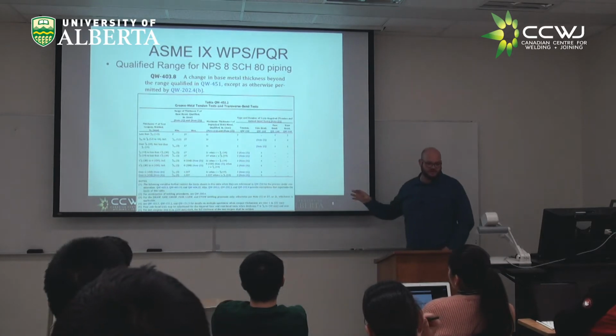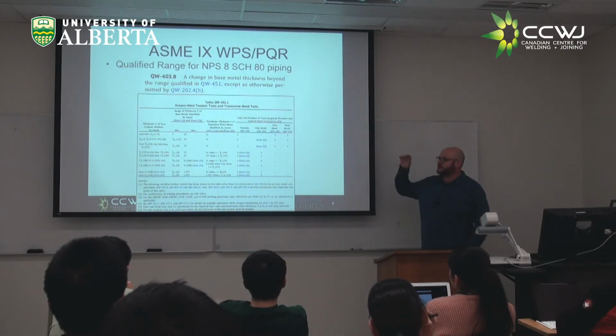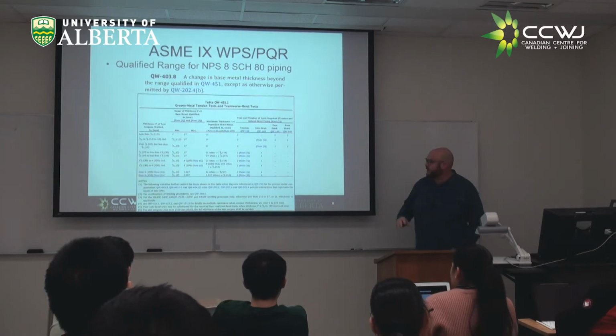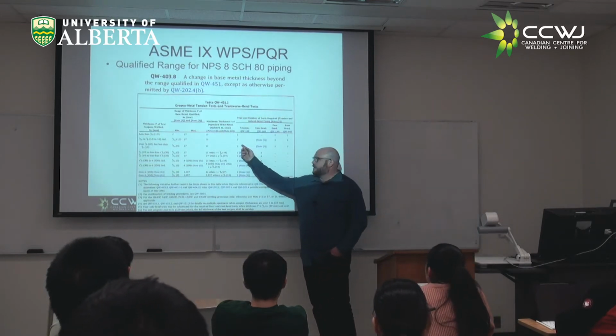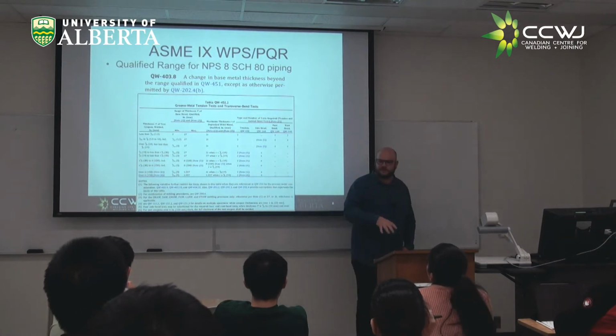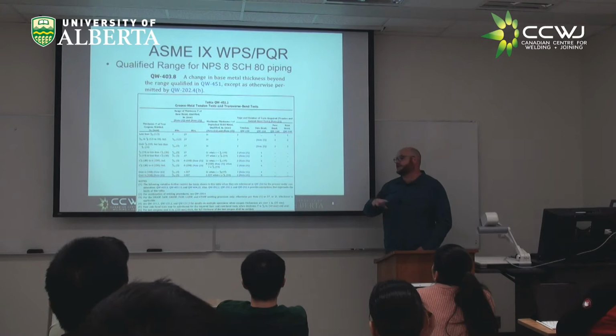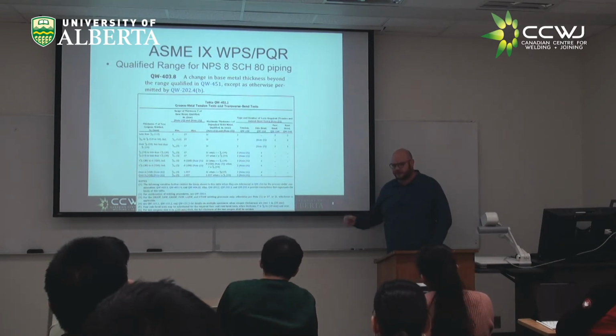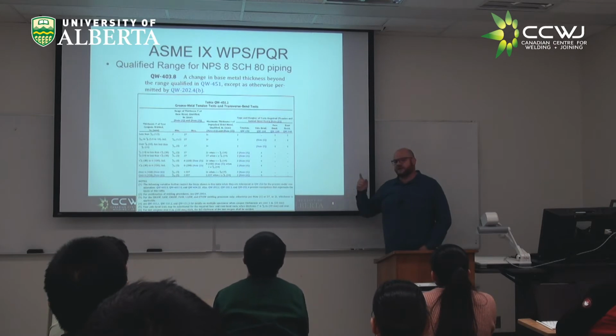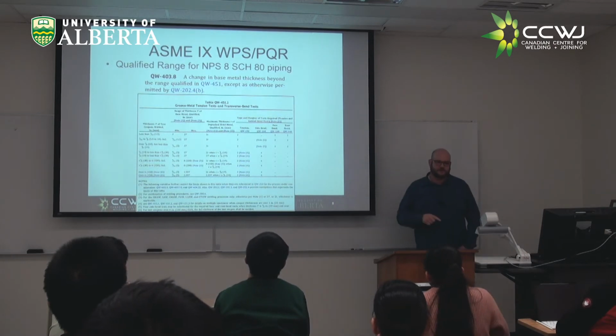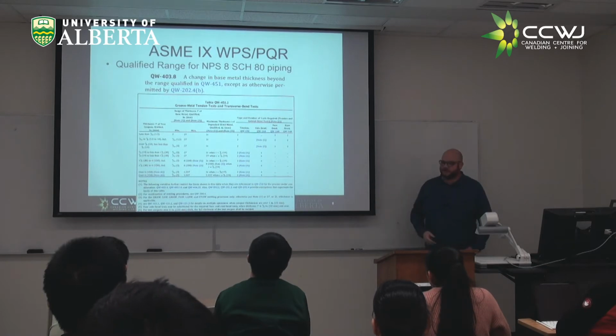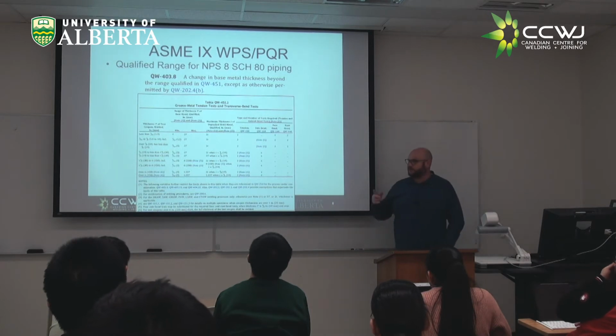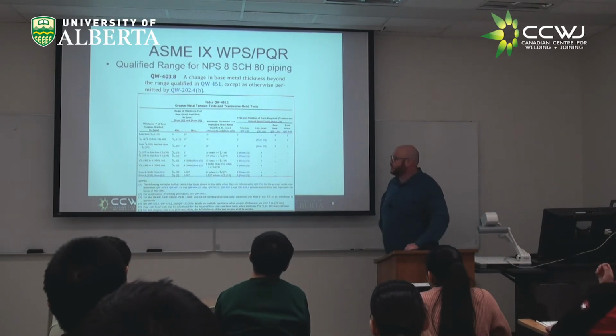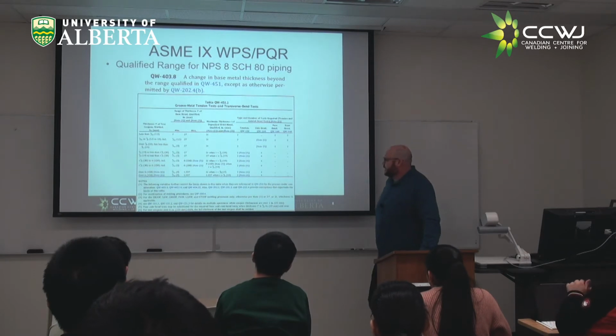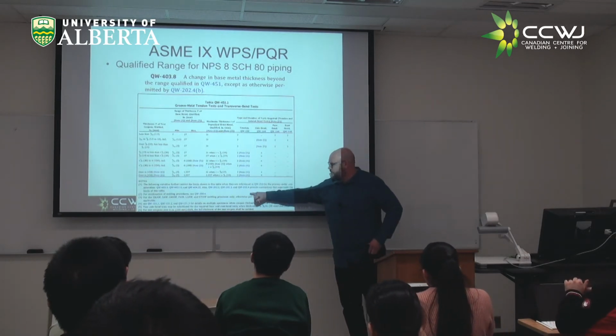The important thing to note that differentiates ASME pressure piping and pressure vessels from pipeline is that whenever they talk about tension tests, the acceptance criteria is always based off of the UTS. That's because the design criteria for ASME is based off of the ultimate strength. Their allowable stress is everything, whereas in the pipeline world, most of it is designed off of the yield strength. So when they talk about tensile tests, they generally want the yield strength as the pass-fail criteria, and the 0.5% elongation under load method is generally what they use. And again, as I said, there are notes that are called out, so there are further modifications.